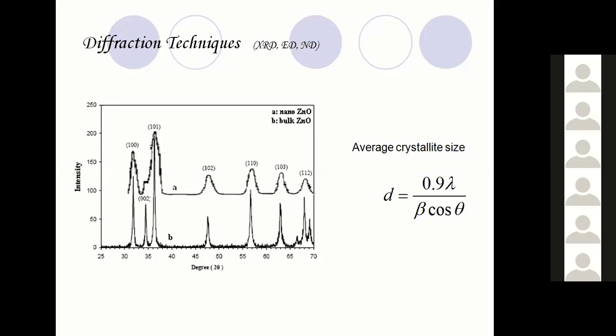This diffractogram was recorded for bulk zinc oxide as well as nano zinc oxide. From the comparison of these two patterns, this is for the bulk zinc oxide, this is for the nano zinc oxide. It has been seen that when the size goes on reducing, the peak goes on broadening. Diffraction intensity goes on decreasing.